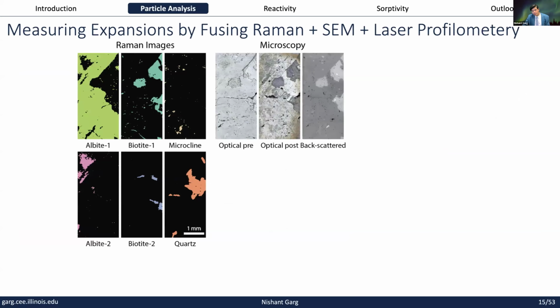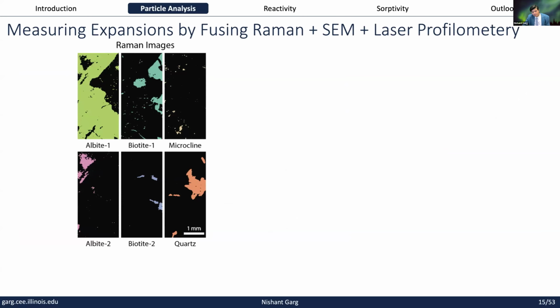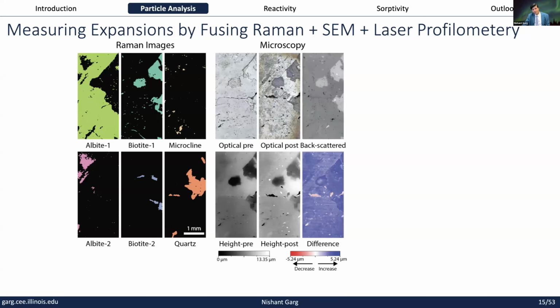Then one of the things we wanted to look at was actually to measure expansion that is happening in these aggregates. This was a grant from the Department of Energy, where we're looking at something called radiation-induced volumetric expansion, where as you subject many minerals in the aggregates to radiation, they can expand. For example, quartz can expand by almost 18%, turning into amorphous silica, and that can be quite problematic for nuclear reactors and the biological shield. So we did some work where we took samples and imaged them before sending them for radiation in Los Alamos.